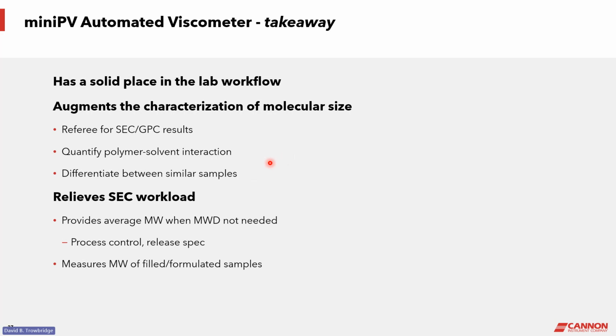And you can also quantify polymer solvent interactions. I didn't talk about this very much, but the coefficients in those working equations tell you something about the interaction between the polymer and the solvent. It might give some indication of maybe chemical composition of various copolymers and how it might be varying between samples. And then also the precision allows you to differentiate between very similar samples.